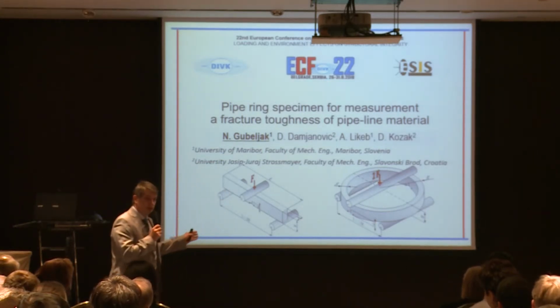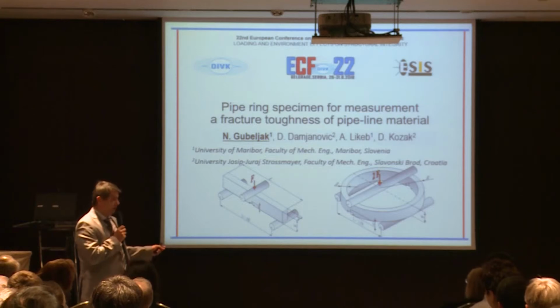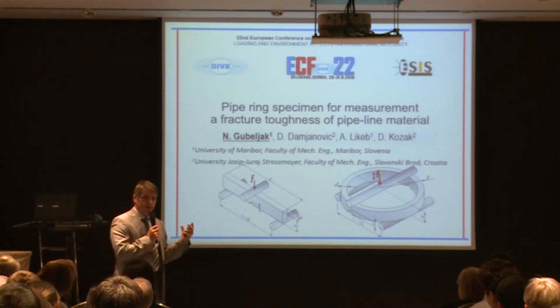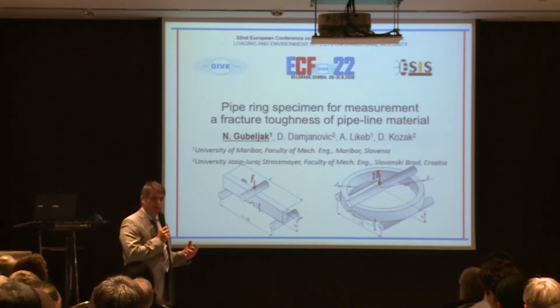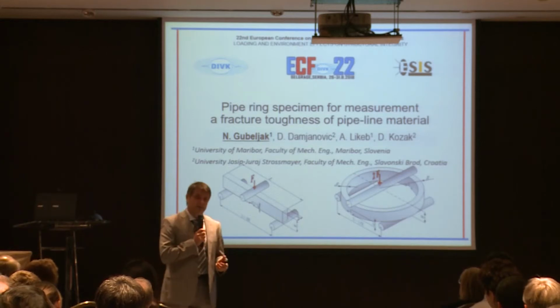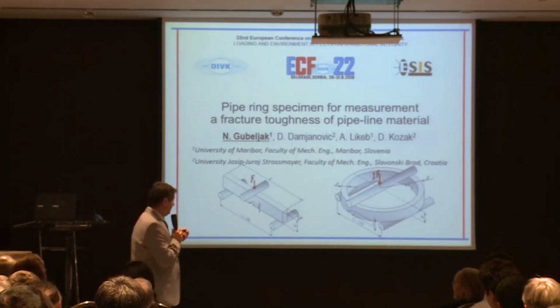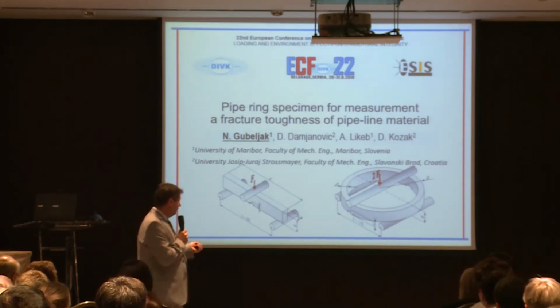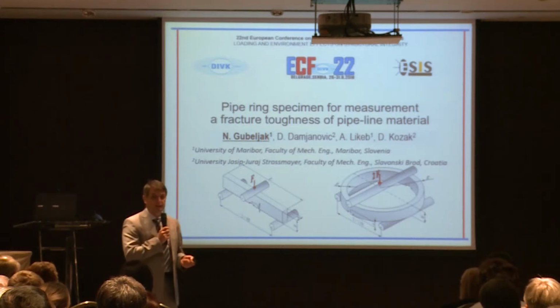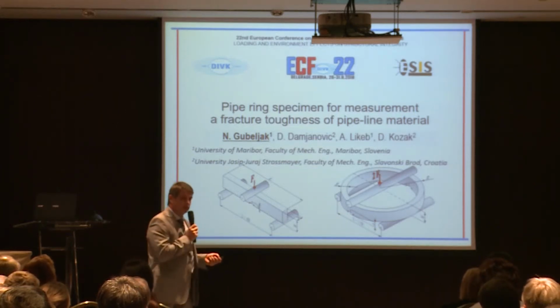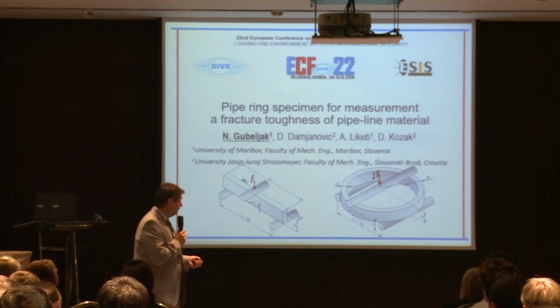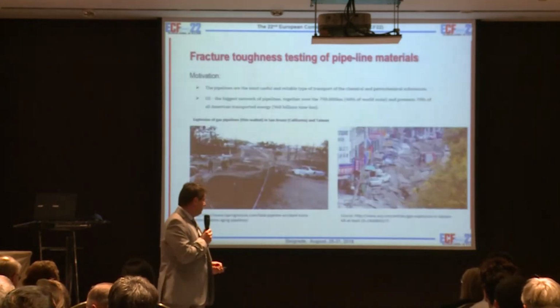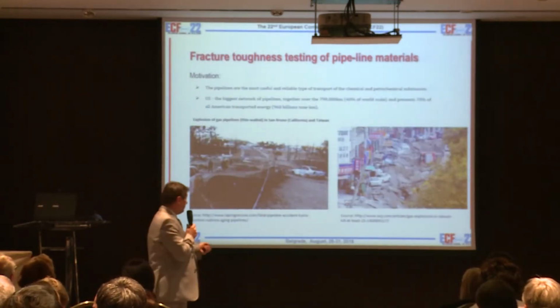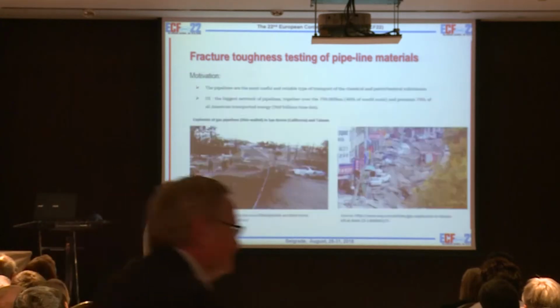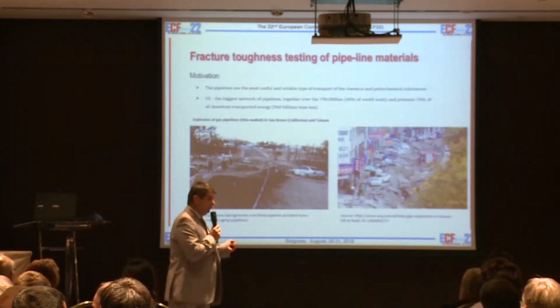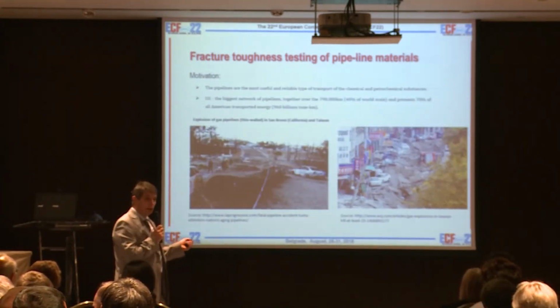So, the idea is presented already here in the first slide. You know that we use the standard 3-point bending specimen in order to determine the fracture toughness. But the idea is how to measure the toughness of pipelines in the case when there is a notch or crack in the longitudinal direction, because often the crack propagates along the pipe, so you have the problem with the toughness of pipelines.